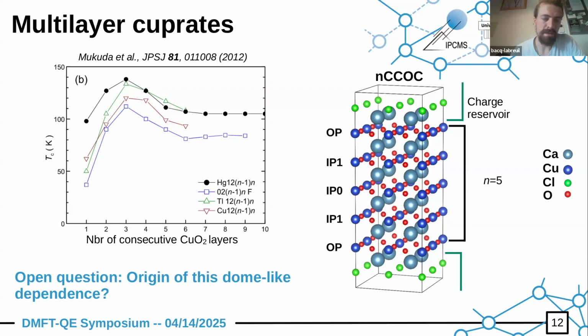And what makes the study of this system quite complicated is that these different planes are not equivalent. So here you can see the labels OP for outer plane and IP for the different types of inner planes. When we dope the system, we dope only in the charged reservoir layers, and so the different types of planes will not be doped in the same way. And even prior to doping, we'll see that there is some intrinsic differentiation between these different planes. This is something that was not, we believe, properly understood before. And so that's one thing that we contributed, I think, to unveil in this study.